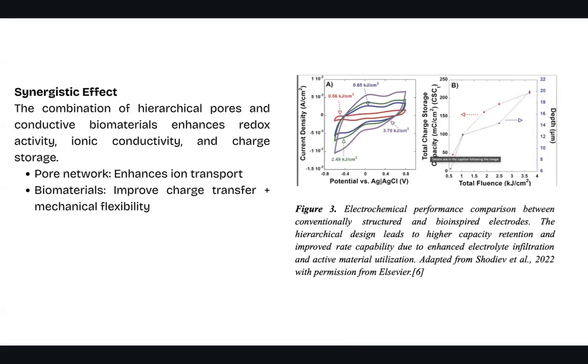So what is the synergistic effect? The combination of hierarchical pores and conductive biomaterials enhances redox activity, ionic conductivity, and charge storage. This includes the pore network, which enhances ion transport, and the biomaterials, which improve charge transfer and mechanical flexibility.